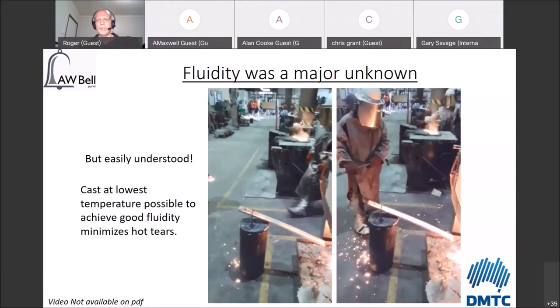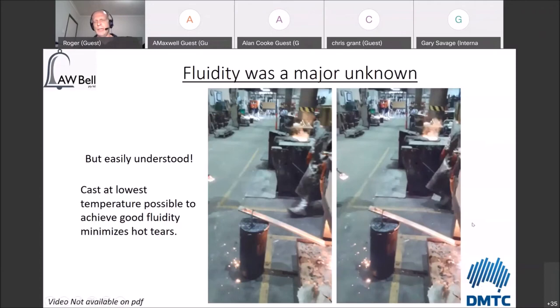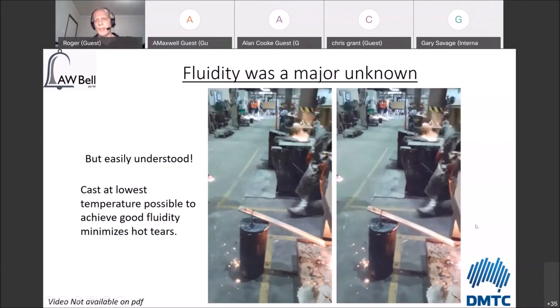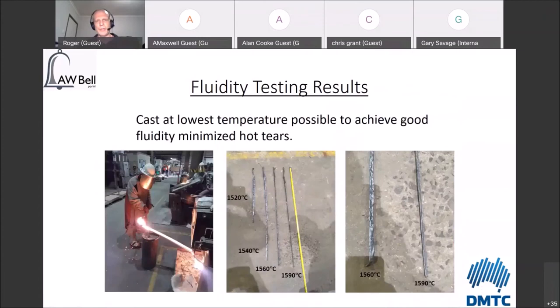So using this test, you're able to get a very good feel for whether my material is likely to fill my mold or not. What you do with this, of course, is run it at different temperatures, and you can see the different temperatures that were examined here: 1520, 1540, 1560, and 1590 degrees Celsius. You take the piece off and you measure it with a tape measure. You start to see that at 1520 it flowed about halfway down, 1540 went most of the way down, and 1560 and 1590 are fairly similar.